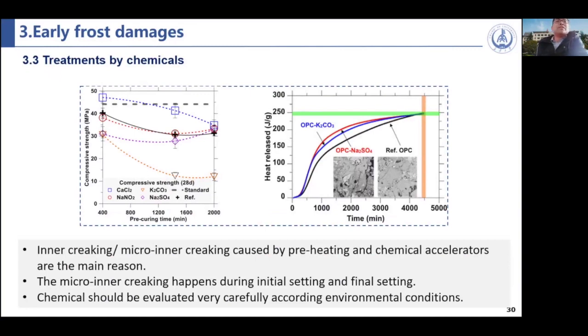We have some discussion and some comments on this phenomenon because the inner cracking or micro inner cracking will be caused by the preheating or the chemical accelerators, which are the main reason to reduce the mechanical behavior or the strength during the early ages, and the micro inner cracking happens during the initial setting and the final setting. This is what we all know before, and the chemical should be evaluated very carefully according to the environmental conditions.